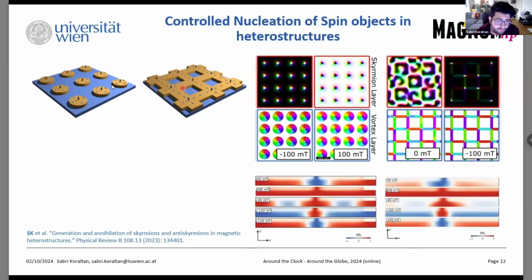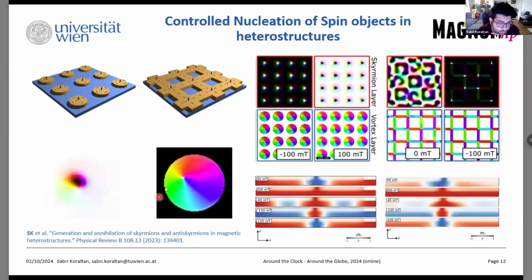By using the vortices or anti-vortices, we can create three-dimensional topological textures, more or less, in which we imprint the skyrmionic states. And the nice part is they are stable. For example, when the vortex core points down and the magnetization outside points up, then a skyrmion can be obtained with the magnetization pointing as we thought. Now when we reverse the vortex core, there is nothing that stabilizes the skyrmion underneath. If you have a look at the work here, the vortex core has already switched, so they are a bit out of sync. We have the black dot, we reverse the core, and eventually the skyrmion vanishes.